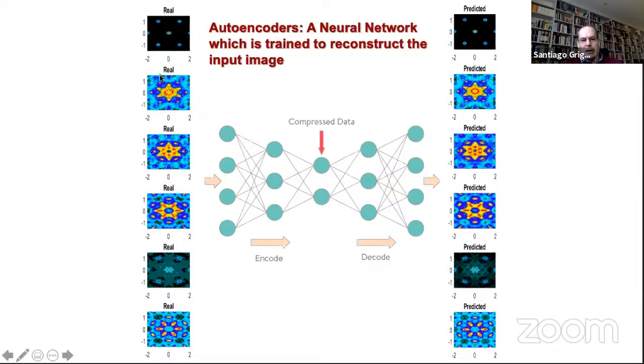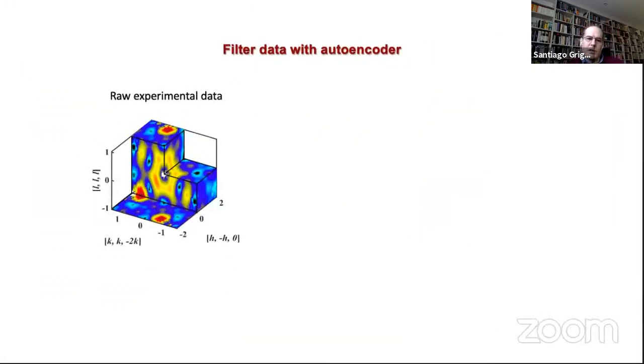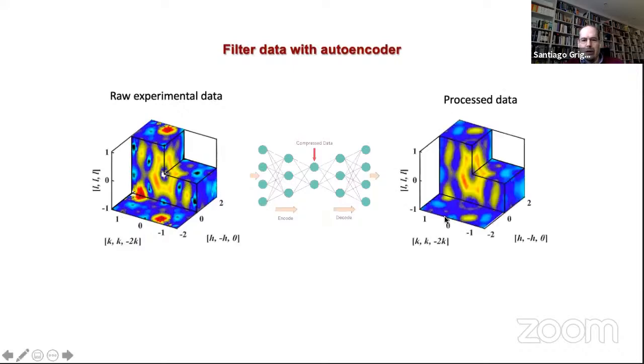So what we did was to take simulations and add noise and Bragg peaks and missing parts to the simulations, and then you ask the neural network to give you back the original simulation, right? And you try this many times till the neural network learns how to give you back what you're looking for. So this is how it works. Then you take the raw experimental data, you put it through this autoencoder, and you get the output, which is the filtered data as well. This is the same as that, but you see that this missing bit is no longer there. These Bragg peaks are no longer there, and well, you cannot see it, but some of the noise is also gone too.